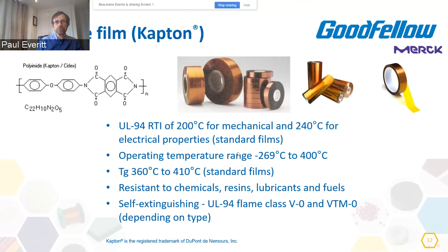It has some drawbacks in terms of its resistance to certain chemicals, i.e. steam. So hydrolytic stability is not good, and also very strong alkali and very strong acid solutions. And it's also UL94 V0 rated, and VTM-0, which is even higher, depending on the type. So it does not catch fire. It just doesn't burn. It will char, which is its way of degrading.